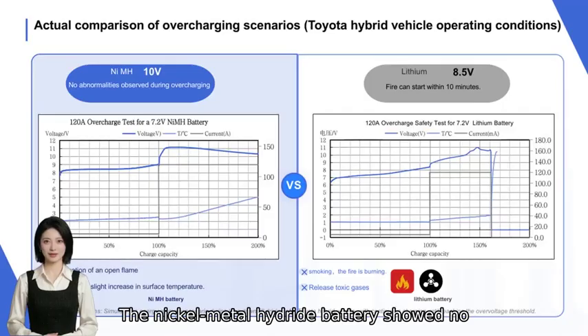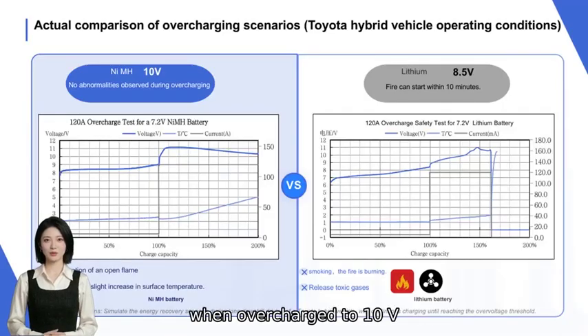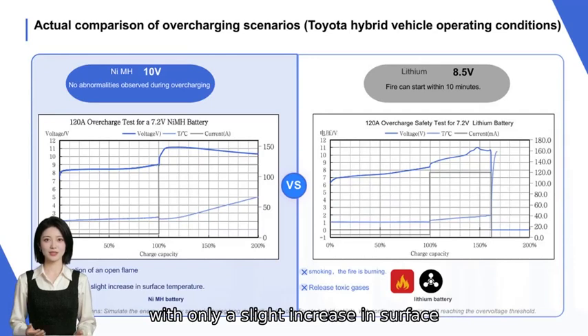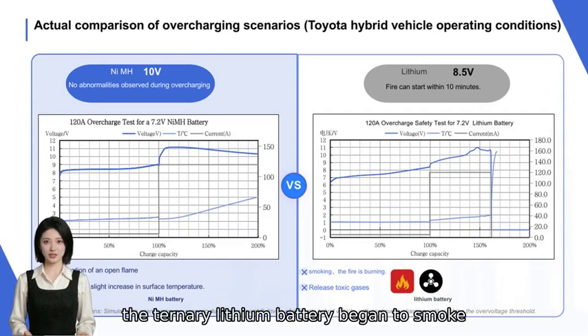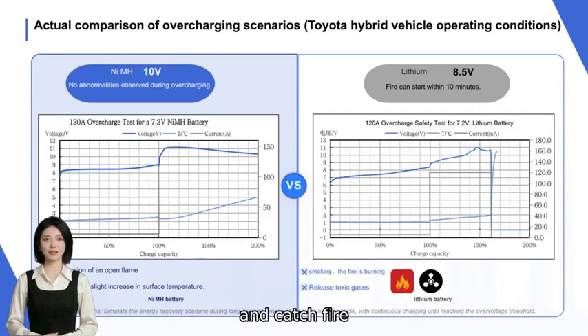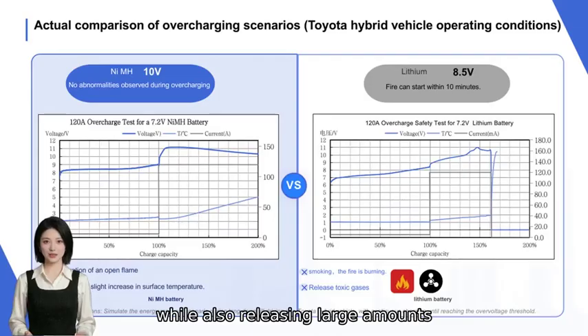The nickel metal hydride battery showed no abnormalities even when overcharged to 10 volts, with only a slight increase in surface temperature. In contrast, the ternary lithium battery began to smoke and catch fire after just 10 minutes of being overcharged to 8.5 volts, while also releasing large amounts of toxic gas.